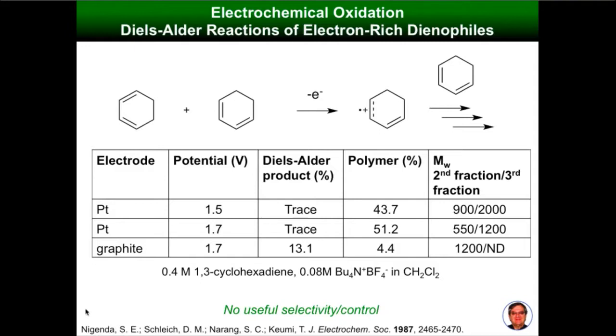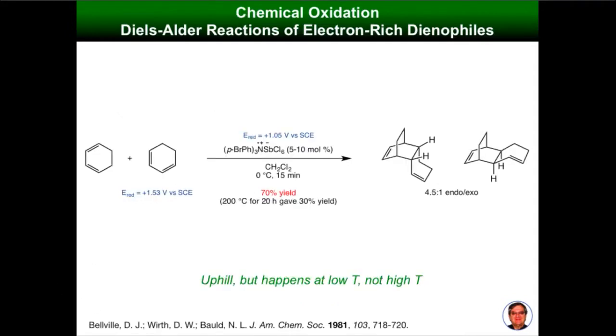If you use a chemical oxidant, you can achieve a stereo-controlled product, a reasonable product distribution. An interesting factor here is that the reaction as drawn is actually uphill, but it happens. It's an interesting question. Why? And it happens at low temperature and not high temperature, but it's uphill.